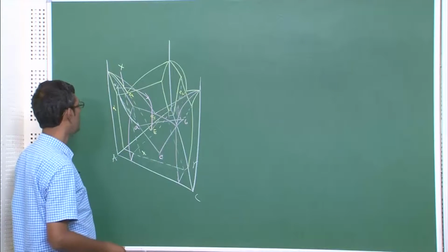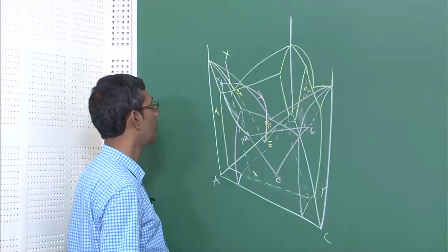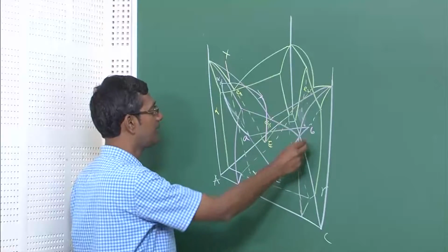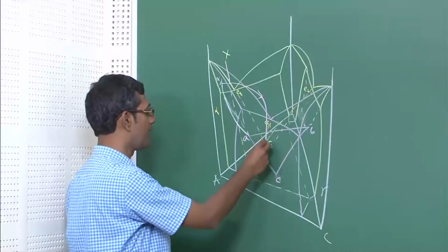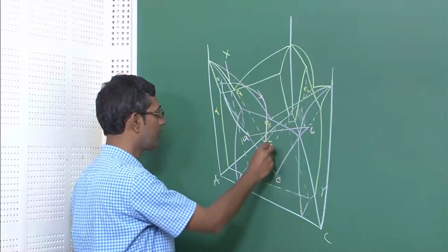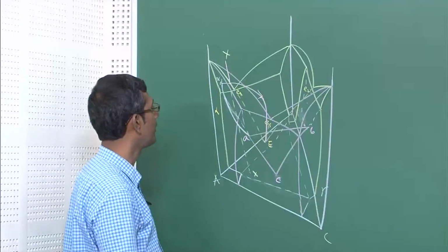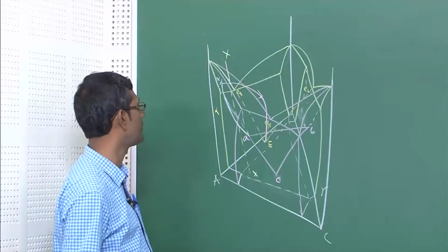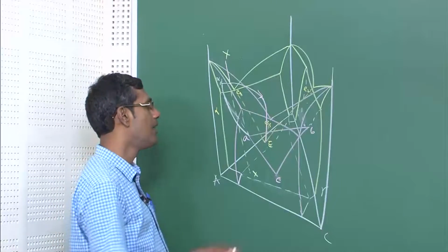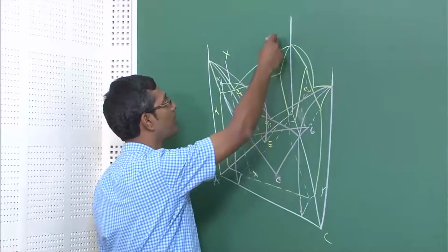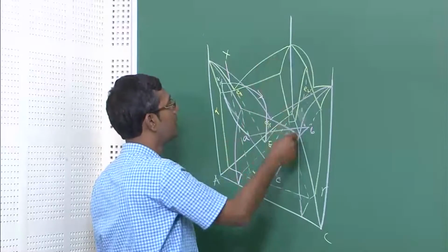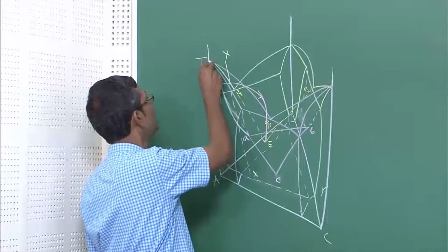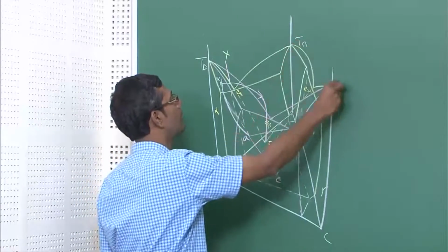Okay. And because of that, what is going to happen? Because of that, liquid will become richer in B more, and finally, it will reach the eutectic composition and it will solidify as a full 3 phase alpha plus beta plus gamma. That is what is going to happen. So, same thing will happen in any of the other compositions sitting on this side or this side or this side of this phase field. That is what you have to draw yourself and try to understand.